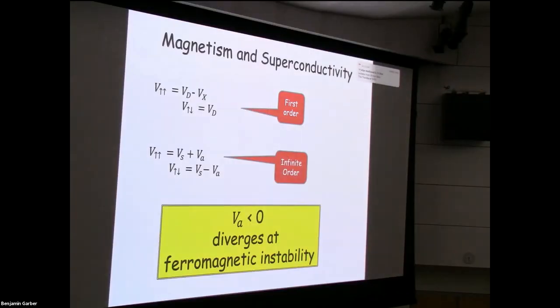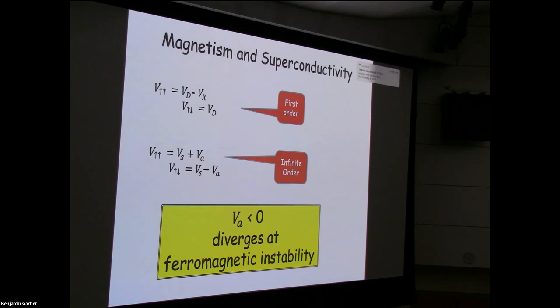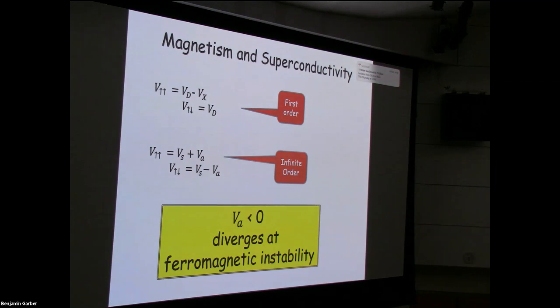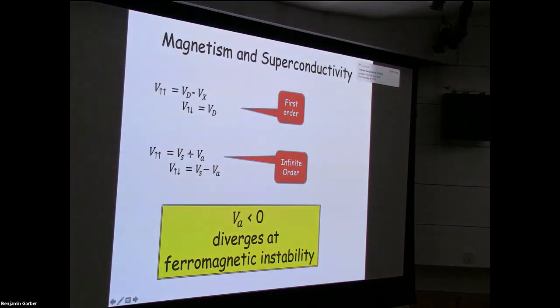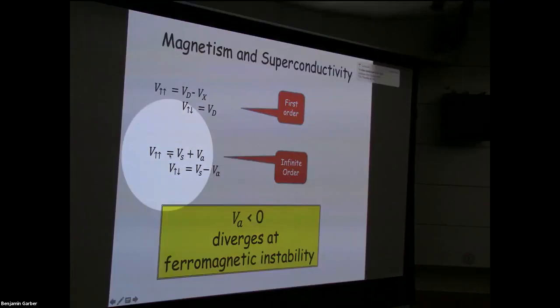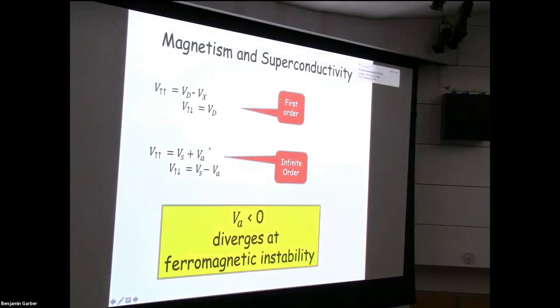What I've written here, there's a connection that's well known, maybe hard to make rigorous, between magnetism and superconductivity. And it's related to the fact that just at first order, the scattering between like spin particles in a metal is weaker than the scattering between opposite spin particles because of exchange interactions which prevent like spin particles from getting close together. And so if you look at that at high order in perturbation theory, it turns out that this difference can be strong enough to make the effective scattering amplitude between like spins attractive. That tends to happen when you get close to ferromagnetism, and the effective interaction between opposite spins becomes very strongly repulsive.